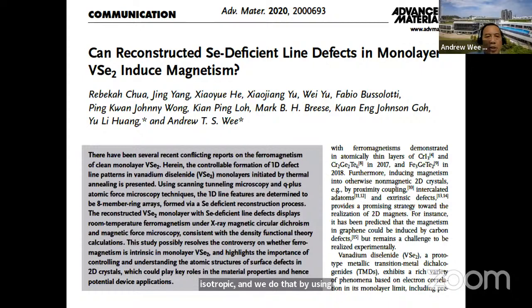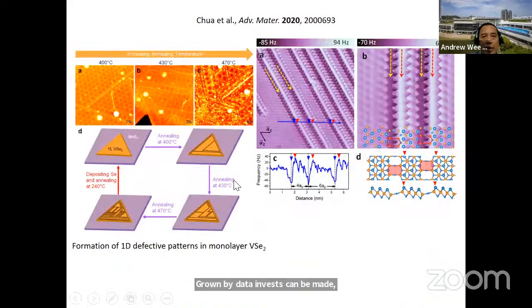So this paper was done by a former PhD student, Rebecca, on reconstructed Se-deficient line defects in monolayer VSe2-induced magnetism. So in this case, we need to find a controllable way of creating defects on the surface. And it turns out that our MBE-grown vanadium diselenide can be made defective by annealing it to higher temperatures. We can get linear defects. You can see defects in these three directions because of the symmetry of the surface.